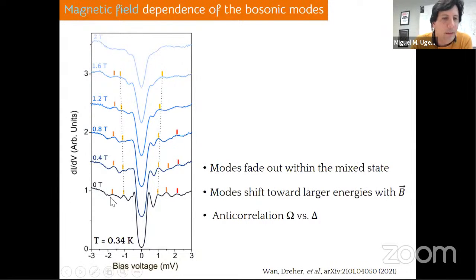And as we increase the magnetic field, the second critical field of this material is around 2.2 Tesla, or well, it depends a little bit on the size of the material, but it's around 2.2 Tesla. So well below the second critical field, you see these resonances become weaker and weaker as we increase the magnetic field, and eventually also die within the mixed state.